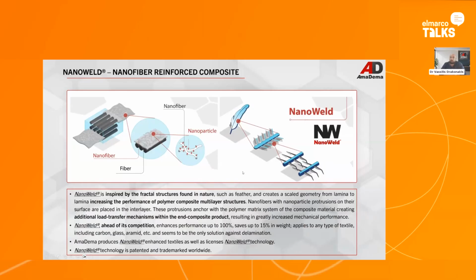But let's see how NanoWeld works. So the real problem in composites is the delamination. The delamination is caused in different ways and for different reasons within the material when it's under load, and basically it is the crack initiation and then propagation within the interlayer that makes the material defective and eventually fail.